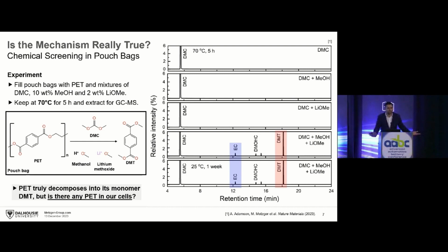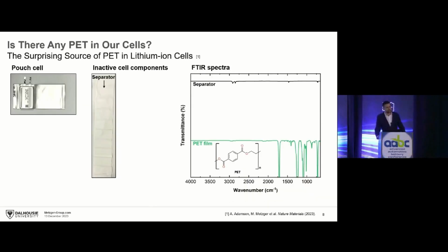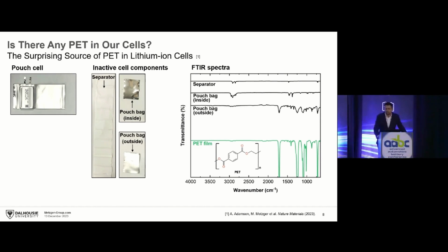So we were pretty sure that this is what happens in our battery cells, but we were not aware that there's any PET in the cell, right? So what we did is we take these little cells, we get them from Lifan in China. It's a multi-layer pouch cell, you can see it up there, and we dissected it, and we looked at any component of the battery and tried to figure out if there's some PET in there. So our first suspect was the separator, and we use infrared spectroscopy here with a reference spectrum for PET at the bottom. And you can see the separator is not made of PET. It's just polypropylene. So we looked at the pouch foil material. So the inside of the pouch foil, which is in contact with the electrolyte, does not show any characteristic absorption bands of PET, but the outside does. But the outside is not in contact with electrolyte, so we also discarded that.